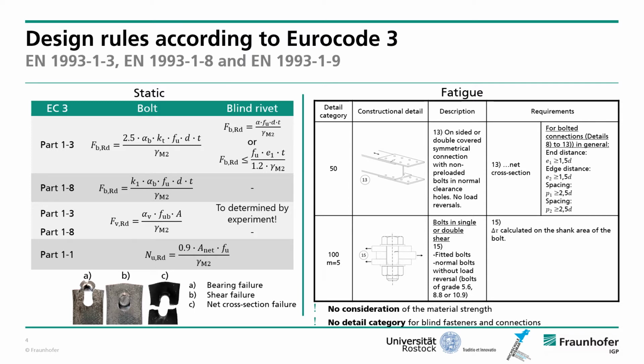In addition, the equation to determine the bearing resistance is bound to additional limitations. For example, the components may only have a maximum tensile strength of 550 Newton per square millimeter. So this means that applications with high-strength steel fall outside this range. For the fatigue strength verification, it should be noted that there are no detail categories for blind fasteners and connections, and also the increasing material strength when using high-strength steel isn't considered in this verification.